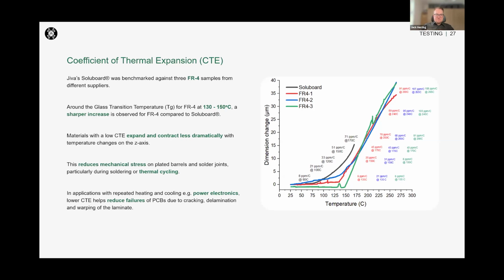So this does mean that because we have a lower CTE, our expansion and contraction is less dramatic compared to FR4. So a lot of the time with the high temperatures of standard reflow ovens, you can see that there might be stress put on plated barrels and solder joints, but this lower CTE in our material reduces the likelihood of any of these failures due to cracking, delamination, warping, etc. So this is something which we are now exploring a bit further, and some of our customers are very interested in.